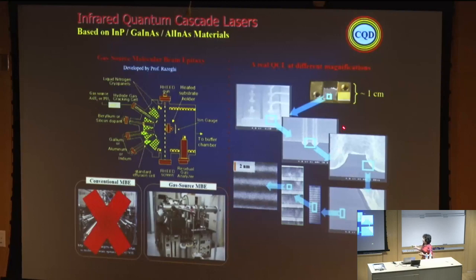Now with the SEM and TEM, if we zoom into each box, here we can see the gold wire bonding on the diode. Here we can see the double channel structure that defines, in the middle, the ridge of the laser. And this part, the white part, is the active layer of the laser. In this structure, the thickness is 1.5 micron and the width is approximately 10 micron.